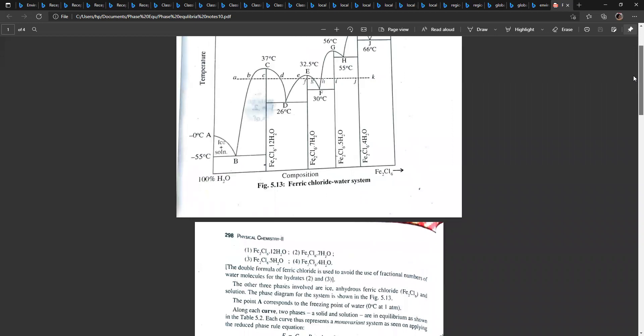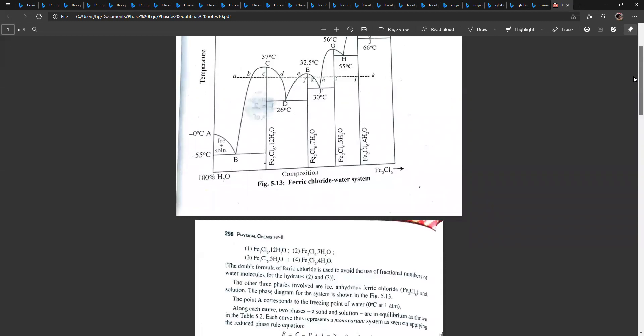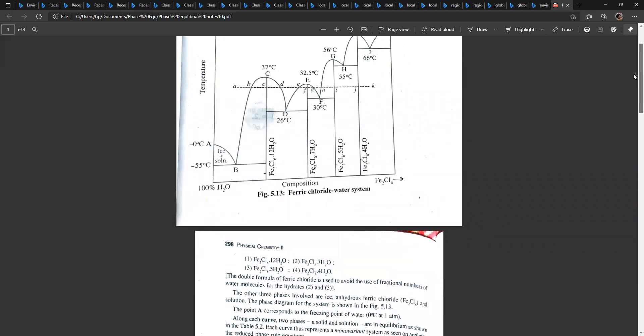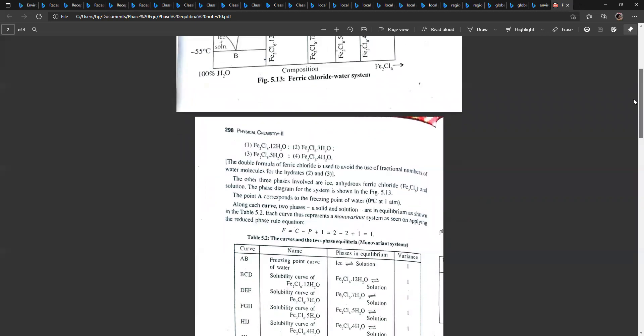At point D, the next stable hydrate, Fe2Cl6·7H2O, begins to separate. The curve DEF is the solubility curve of Fe2Cl6·7H2O. The phases in equilibrium along this curve are Fe2Cl6·7H2O and solution. At point F, the next stable hydrate, Fe2Cl6·5H2O, begins to separate, and curve FGH is the solubility curve of Fe2Cl6·5H2O.